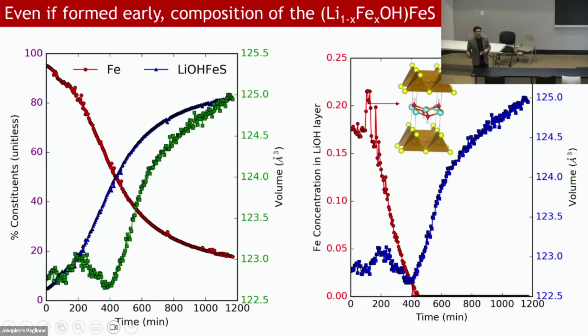So sometimes when we do syntheses, we get results that are not reproducible, correct? And I think one of the things that can happen during an actual reaction is, depending on when you remove it from the furnace or from the oven, let's say for hydrothermal, you may get a different composition than you think you started out with. Many times we write out in a publication a nominal composition, right? That's what we think we put in there. But what you actually get out is much trickier to really know, and you have to do both the diffraction analysis and some other kind of compositional analysis in order to verify.